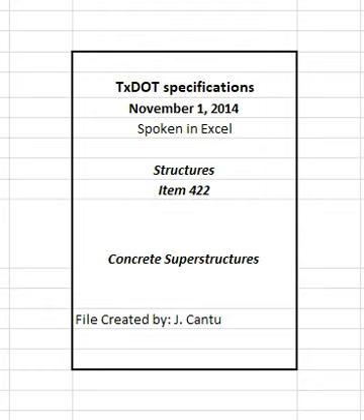4.6.13.3 Placements on continuous steel units. Place slabs on continuous steel units in a single, continuous operation without transverse construction joints using a self-propelled transverse finishing machine or a mechanical longitudinal screed unless otherwise shown on the plans. Retard the initial set of the concrete sufficiently to ensure concrete remains plastic in at least 3 spans immediately preceding